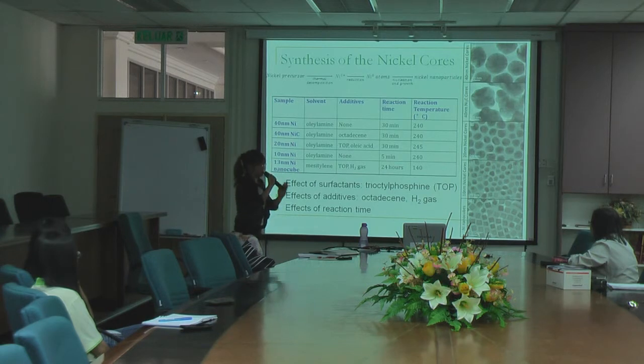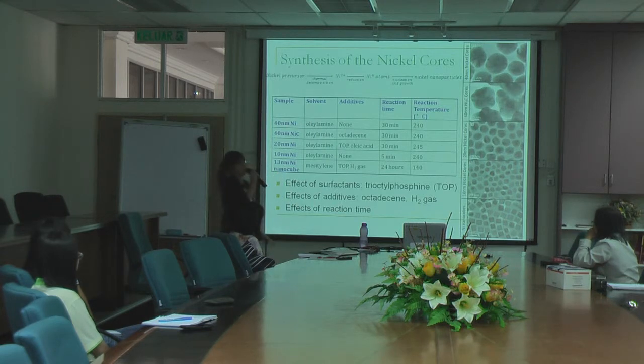So the more important point is how to separate the cadmium selenide that is not attached to the nickel. What we can do here is quite helpful: nickel is magnetic, so we can use magnetic separation to separate the composite from the cadmium selenide that is not attached. So you already collect them before you do the analysis? Yes.